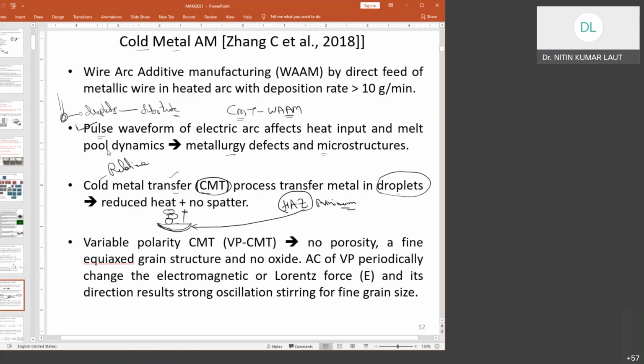So you also work with this electromagnetic force or Lorentz force. Okay, you can play with this force because you will realize that in this weld pool dynamics, this electromagnetic force plays a major role in developing or controlling the defects. And because we are changing this variable polarity, one of the biggest advantages we get here is a facility of stirring or mixing the droplets or the composition of the droplets, so that you get a good fine grain size, which is very much required to have good strength in your material, the substrate.